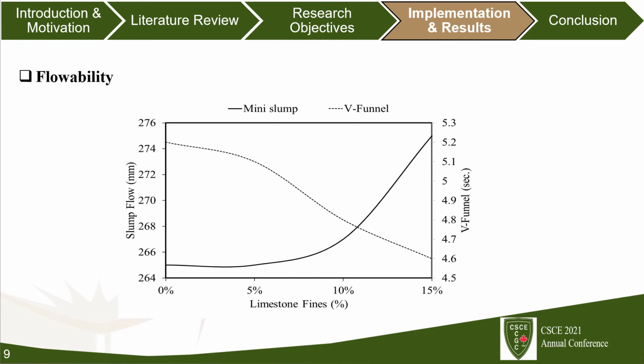So, for our result, first I examined the flowability of the self-compacted mortar. As you can see here in the graph, all the self-compacted mortars flow in the recommended range between 250 and 300 millimeters. Besides, they maintain a flow time in the recommended range between 2 and 10 seconds. The flowability was enhanced by increasing the percentage of limestone.